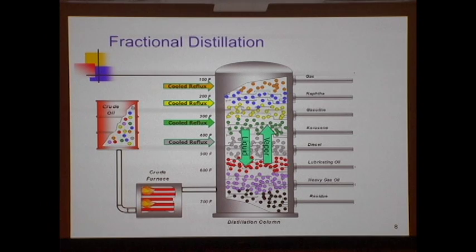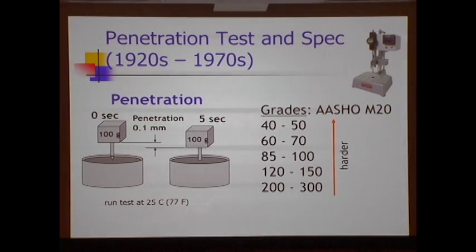It was a separation process, very simple, and it had a specification that went along with it that was also very simple. Everybody's mentioned the penetration. It seems like every speaker practically has mentioned the penetration test. And it's like Darren said, we never get rid of anything. We just sort of keep it along for the ride. Basically, this was a test that was sort of an indirect indicator of the viscosity of the asphalt, or the consistency of the asphalt.